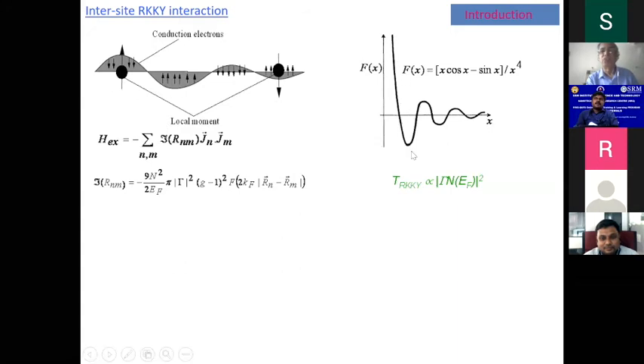But there is an oscillation of the polarization, in other words up and down slowly like a wave. The conduction electrons get polarized by the local 4f electron, or any local moment sitting there. That is basically the mechanism of magnetic ordering in any metal. It is a very important interaction. If one local moment is sitting here and another local moment here, these two can be antiferromagnetic, because the conduction band polarization is opposite here. It's called RKKY. This goes like the square of the exchange interaction, the interaction strength gamma between the local moment and the conduction electron.